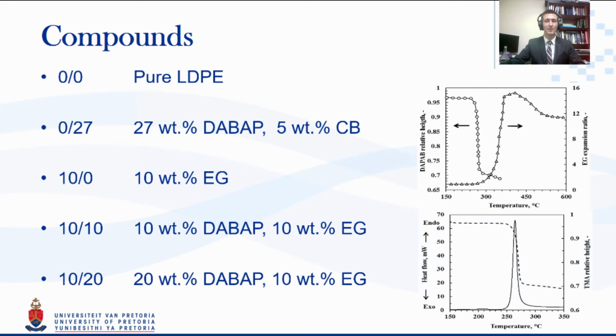So for the next compound, we did a similar thing, but here we could actually look at the TMA. As you can see here on the right, you'll find that the softening event of diaminobenzoic phosphate occurs at a temperature of 257 degrees, and that this is actually before expandable graphite, even the low temperature expandable graphite, expands, which is exactly what we want, because this would mean that once that material has softened, as the expansion event occurs, all of that material expands through the DABAP and then gives this cohesive thermal barrier.